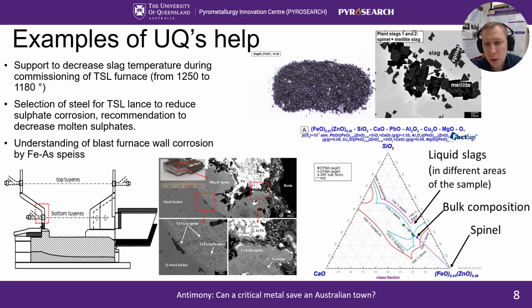But in discussions, it was understood that this high operating temperature is not sustainable in the long run because it results in increased hot corrosion of the furnace lining made of refractory ceramic materials. In smelting operations, the fast loss of refractories is the major financial risk because the repairs require full stopping and relining, which is a huge operational loss.